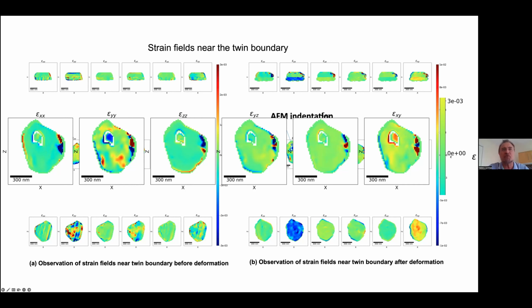But it would be great to have any experimental proof, you know, and this effect is so huge that it should be visible. And also what we found is that this dislocation pileup in simulation is localized at the grain boundary. Right. So it should be a large step, and it's independent of grain size, which is important, but it's just focused at the grain boundary. Yeah. Which makes my head race along in terms of what kind of beam we should send through it and how to interrogate it. And Saryu is probably ahead of me in terms of having thought about the problem. But yes, there are a number of different ways that one could try to sort of creep up on the problem, as it were.